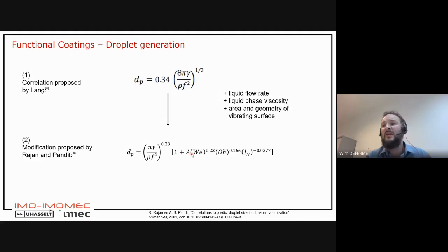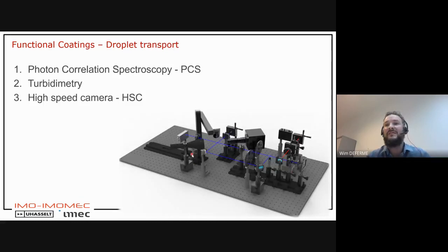You generate your droplets, you can calculate based on the liquids, based on the rheological properties of your liquid, what to expect from droplets. But then, of course, if you go further, you really want to see, is it true? Are the droplets that we generate, droplets that we fire towards a substrate, really the size that we expect? So then we had some research together with the Max Planck Institute in Mainz, where we developed a measurement system to measure these droplets, and we used photon correlation spectroscopy and turbidimetry to measure not only the size or the diameter of the droplets, but also the speed of them, and then we compared that with high speed camera images to compare the technologies with each other.